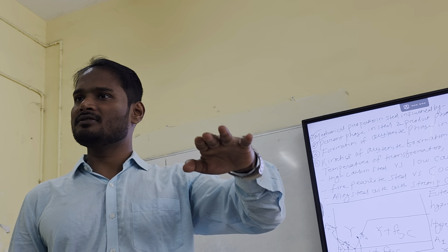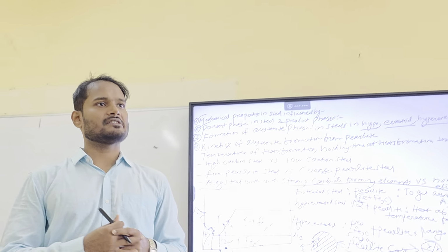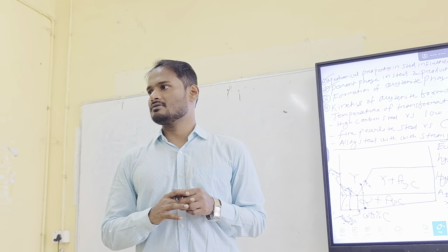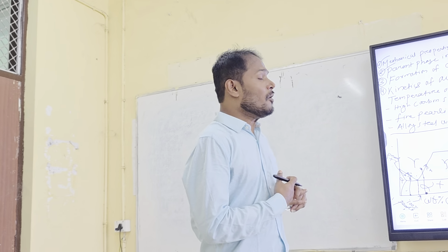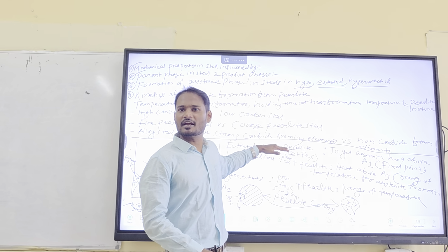So it occurs by a nucleation stage and a growth stage. And how is nucleation happening? Because of diffusion of carbon from cementite to the interface. More diffusion, more nucleation, and finally the entire ferrite will get consumed by this gamma, and it will become bigger gamma. So gamma will become very big because of consumption of ferrite. This is called the growth stage. Nucleation and growth stage.